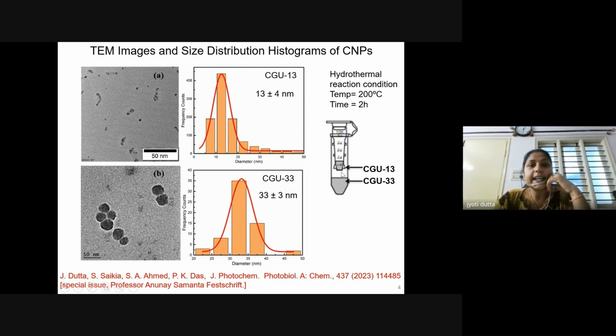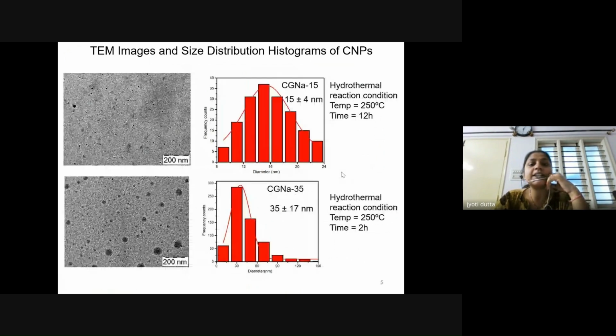Further, the second set of carbonaceous nanoparticles consisted of glucose with NaOH as the additive. We have not used any urea here. In this particular case, we observed that the size of the carbonaceous nanoparticles varied with the reaction conditions. So 15 nanometer carbonaceous nanoparticles were observed when the temperature was 250 degrees centigrade and the reaction time was 12 hours.